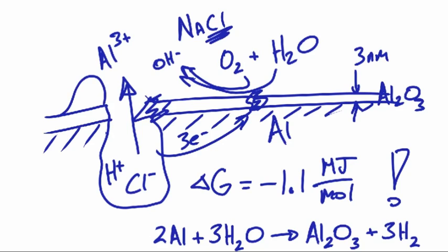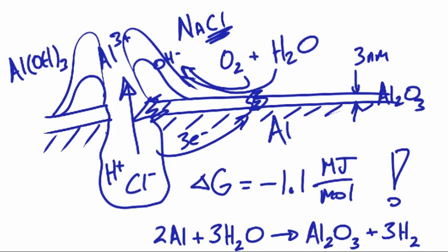Now the aluminum which is released reacts with the water outside the pit and it forms a chimney of aluminum hydroxide. The pit becomes so acidic that we can start having hydrogen reduction or hydrogen evolution and hydrogen bubbles start bubbling up out of the pit. So we have the H2 form.